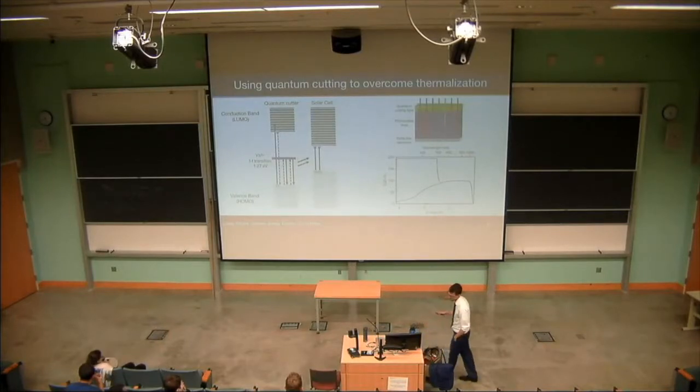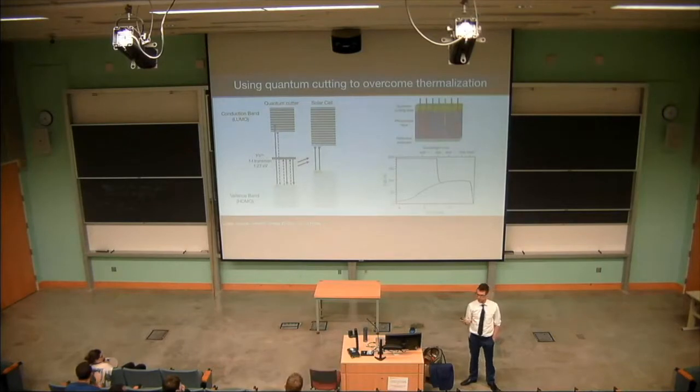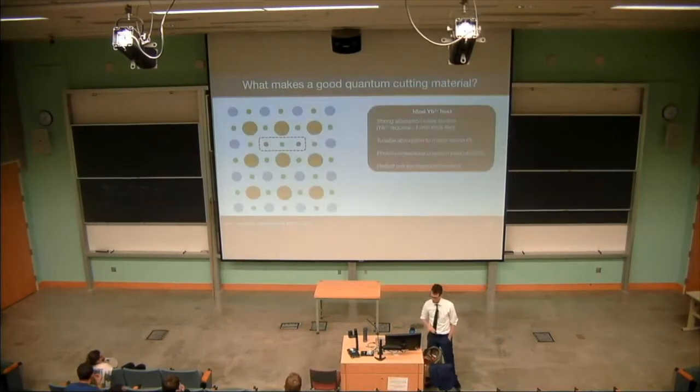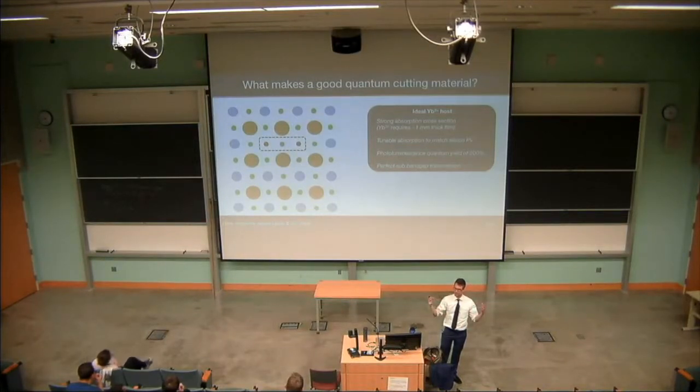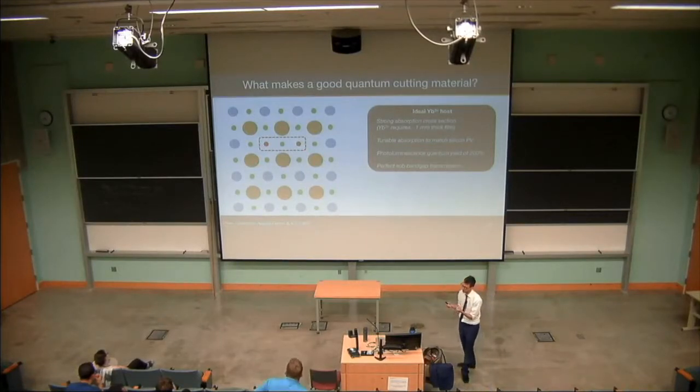And as I mentioned, materials that have this property, for a wide variety of reasons, are fairly isolated to ytterbium dopants, or at least as a material that has this property in the visible region. One problem with this is that in order to transfer that high energy absorbed photon to 2 local defect states, they have to physically sit close to each other to be in electronic communication. This means that we have to form this kind of defect that I talked about earlier, where you have 2, for example, ytterbium atoms sitting very close to each other in the lattice.